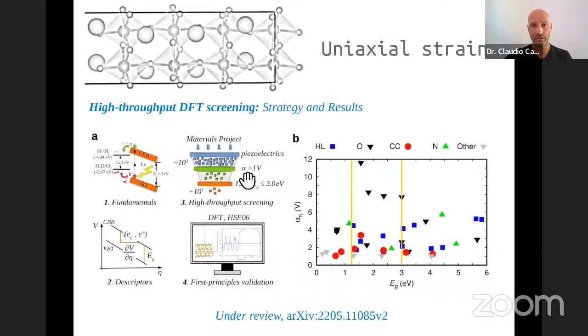Again, the larger the value of this parameter in our modeling, the better the material in terms of band alignment tunability. But of course, because it's not just about moving around the band alignments, it's also about the energy band gap. From the materials that fulfill this first condition, we finally selected those that also had optimal energy band gap traits, right? So basically, a band gap in between 1.2 and 3 electron volts. So we did that for over 1,000 materials, and from all those, we found a total of just around 40 materials that fulfill this first condition, and from those 40 materials, only about 20 fulfill this second condition, right?